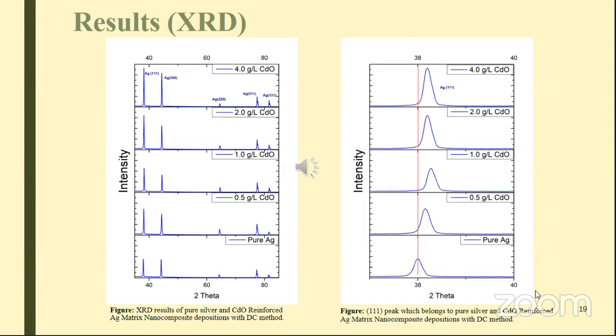And from the right figure, the highest full width half maximum is observed due to the finer grain size in the 1 gram per liter nanocomposite coatings. This result is confirmed with the 1 gram per liter nanocomposite SEM images. Also, the most shifted 111 peak belongs to the 1 gram per liter nanocomposite deposition due to increased hardness and strength.